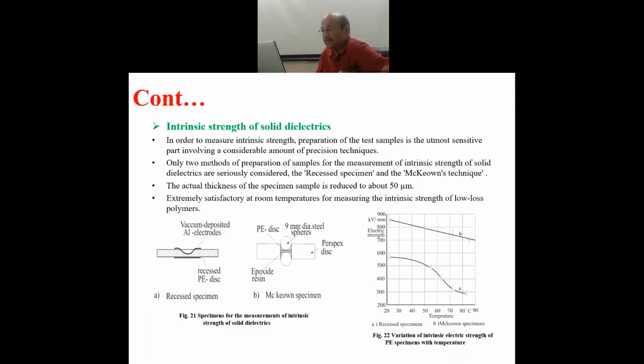When the temperature increases, it affects adversely the strength of the solid dielectric. And as you can see, the lower breakdown strength is measured at higher temperatures, to the tune of, say, 80 degrees centigrade. So when it is normal temperature of the order of, say, 20-25 ambient temperature, the breakdown strength is of the order of 850 kV per millimeter. It's a very, very high, unbelievable breakdown strength. So that cannot be measured in a simple fashion everywhere.